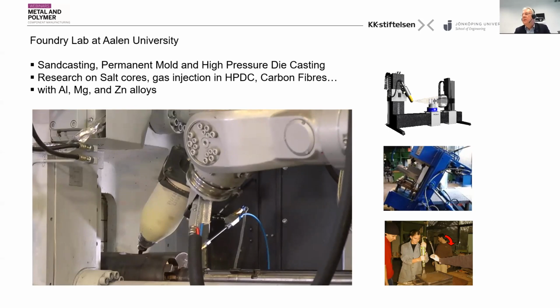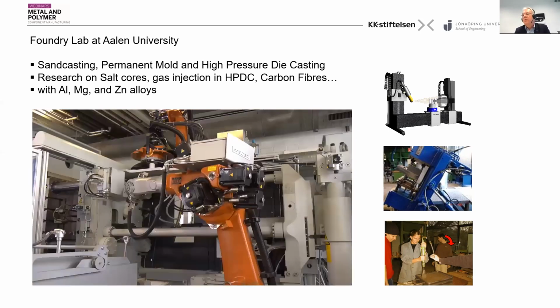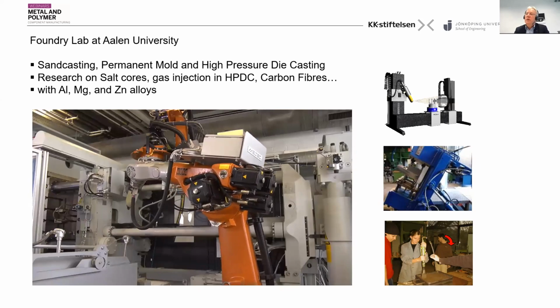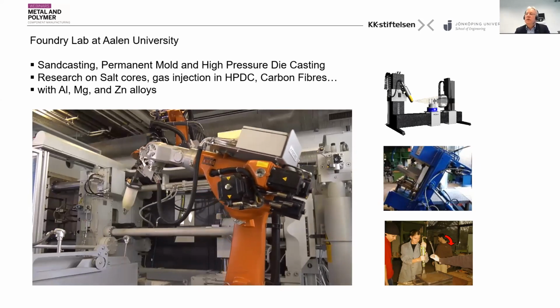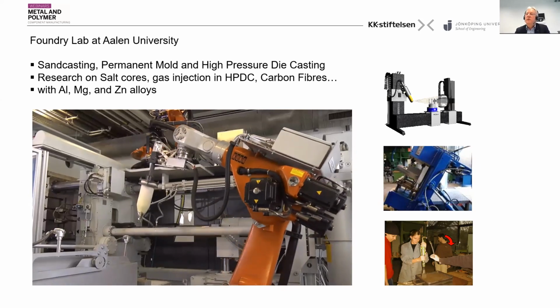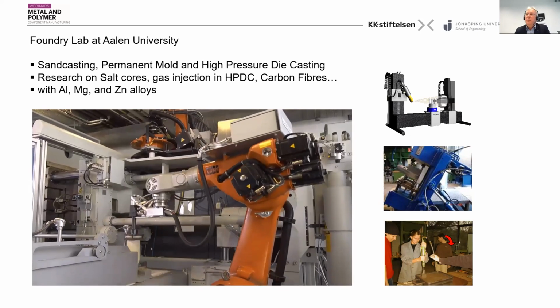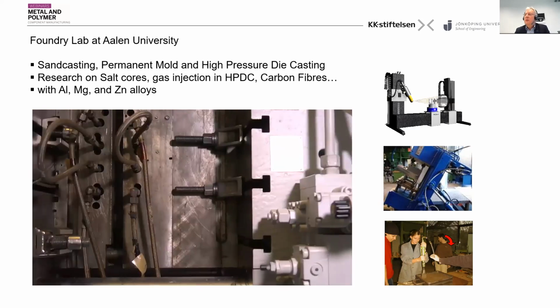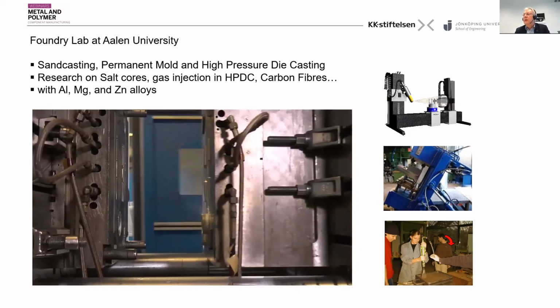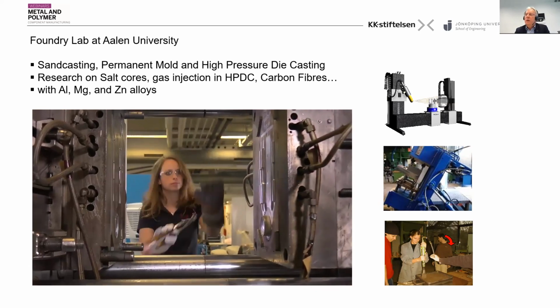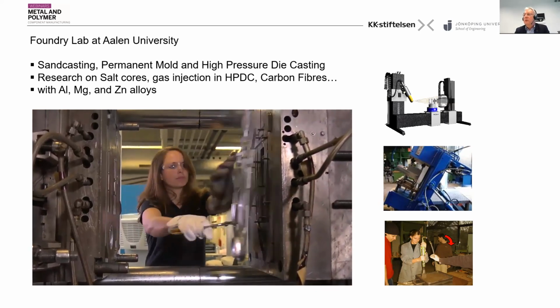And so this is the plunger. The shot is coming now. It's moving relatively slow at the beginning, but fast during filling to get very short fill times. And then we can open up the die and have a very nice part, which is typically taken by a robot, again in an automatic production cell, but here we do it manually.